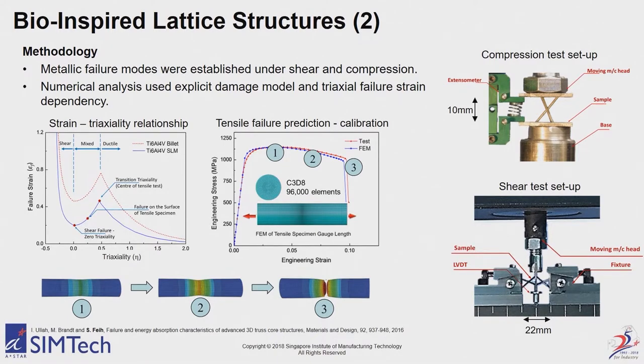And generally, we were seeing very similar trends to cast material. Just the failure strain was a bit lower, and that is due to the fact that under additive manufacturing, you actually get a different microstructure. It's a bit more martensitic for titanium 6-4. This wasn't heat treated, so the failure strains were lower. Okay, but does this failure model now translate to the failure model for the lattice structures?